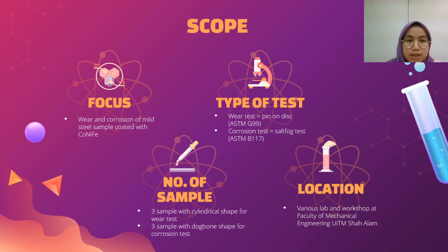The scope of this study is focused on the wear and corrosion of mild steel sample coated with CoNiFe coating. Number of samples that will be tested are 6 samples, where 3 samples will be tested according to ASTM G99 pin-on-disc test, and another 3 samples will be used for ASTM B117 salt spray test.